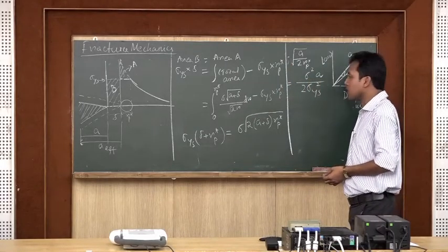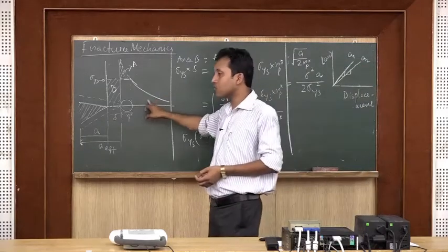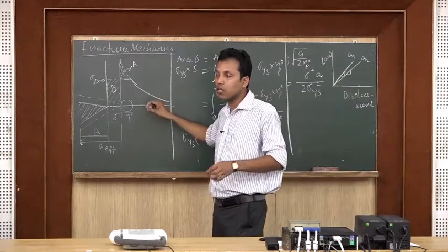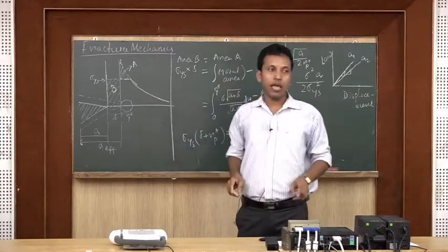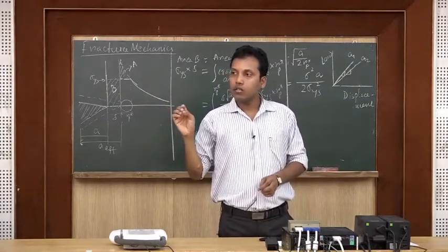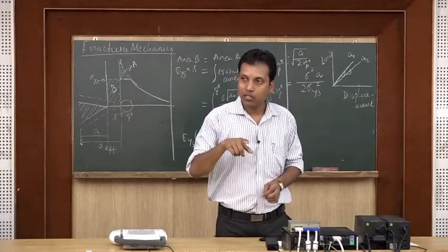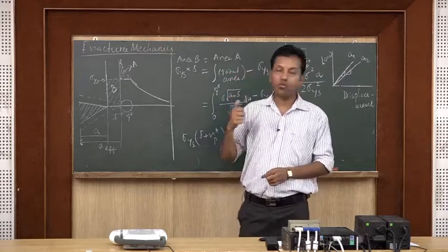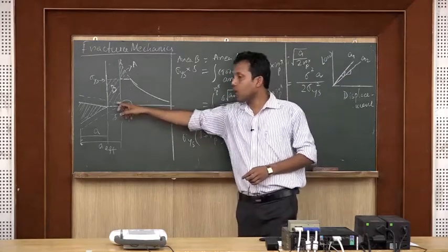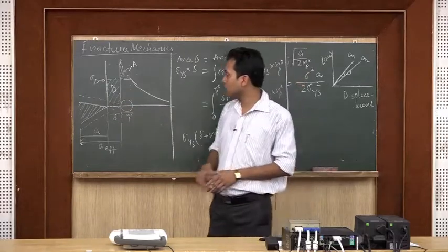So, here we are seeing that a big crack length means lower stiffness, and that the presence of a plastic zone also means lower stiffness. So we are correlating these two, as if, in addition to the crack length actually present, there is another crack of somewhat larger length. So we have the idea of a virtual crack length. Virtual crack length of how much?